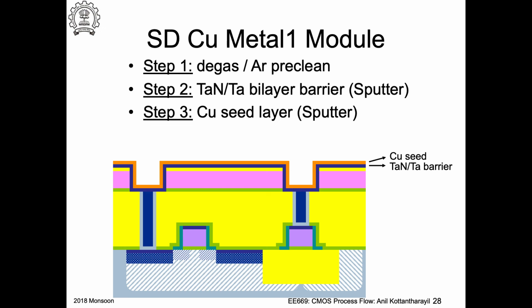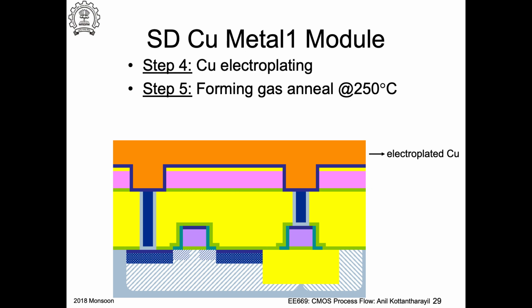Then you deposit a thin layer of copper by sputter deposition. Okay. So apparently it is quite difficult to do CVD of copper. So you deposit a very thin layer, and then you can see that you are going to cover this entire wafer surface using copper. Okay. So you want to grow thick copper, and by this technique, what you would do next is electroplating. Okay. And subsequently you will do a forming gas anneal at fairly low temperature compared to what we have seen for source drain implant anneals, thermal oxidation, thermal CVD, and so on. Right?